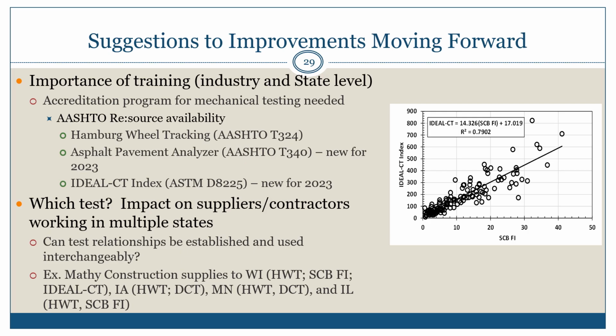Also, we have to consider that if states are going to have multiple tests, there should be some sort of standardization between these tests. There are some border states that may want to use completely different test methods, which would require an asphalt mixture supplier to conduct multiple tests to get their mixes approved. You can see some examples below from Mathy Construction, who produces and supplies material for Wisconsin, Iowa, Minnesota, and Illinois, and the number of different tests that they have to conduct to satisfy the respective state agency. This can be very complicated and cumbersome for an asphalt mix supplier. So if there's a way to simplify this, maybe establish some sort of relationship between test methods that would allow for similar criteria, it could certainly help asphalt mix suppliers that are supplying to multiple states.